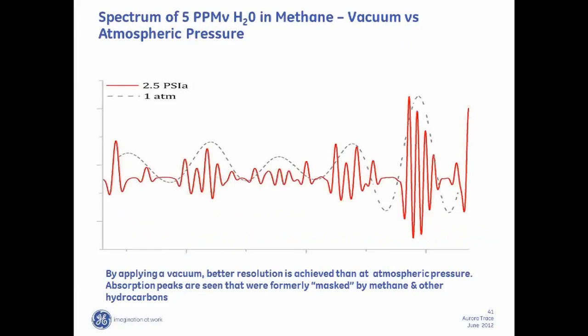There's actually about 5 discernible peaks that come out under the vacuum condition, and there's one sort of broadened peak that comes out under the atmospheric condition that's attributable to water. This is particularly interesting when you're looking at low levels because many of the hydrocarbons, such as methane and ethane, have co-absorption characteristics at these very low levels, and under higher moisture concentrations, their absorption values are negligible. But when we're dealing in part per million levels, they become more significant. So we're able to get rid of those effects or negate those effects by applying a vacuum to this system.